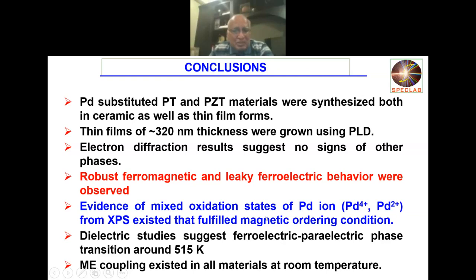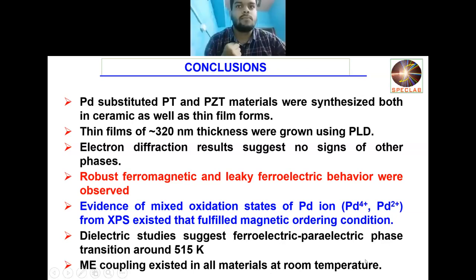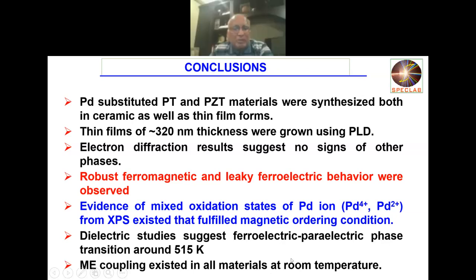Evidence of mixed oxidation states, that is the palladium ion being Pd4+ and Pd2+, were both clearly seen through XPS data. And that is the one that gave the magnetic ordering in this material. Otherwise, you should not be getting any magnetism in this material. Dielectric properties suggest that there is a transition around 515 K, which is a ferroelectric transition, of course. And the ME coupling existed in all materials at room temperature, though it was low in this case compared to what we got for the solid solution material of PFT-PGT.